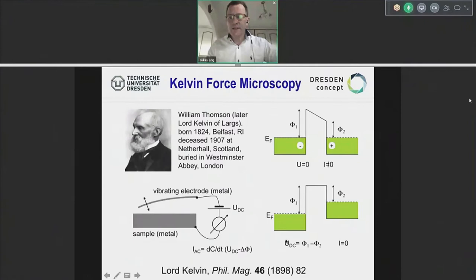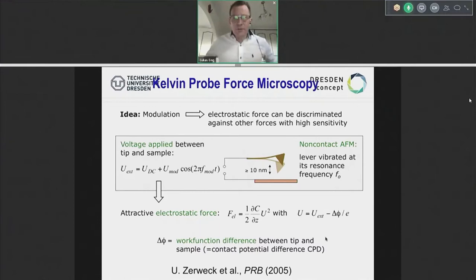Well, scanning force microscopy is ideally suited to incorporate this Kelvin probe force microscopy. That means using the cantilever, applying an AC and a DC voltage, vibrating it, and hence getting an electrostatic force in addition, where you get access to this phi again. This is the work function that we already saw in STM. You remember the work function drawing that I was showing before. So now we have access to it as well through a completely different mechanism. And it was Ulrich Zerweck who proposed, back in 2005, a very elegant way to measure this. So let me show some results of this.